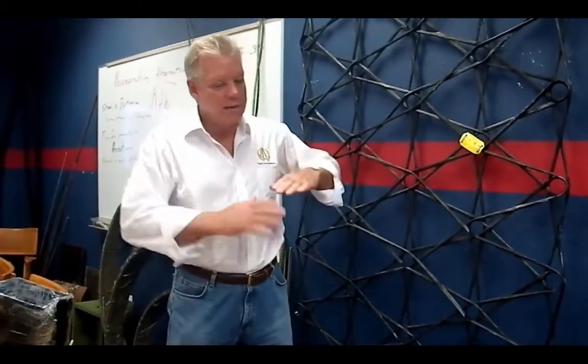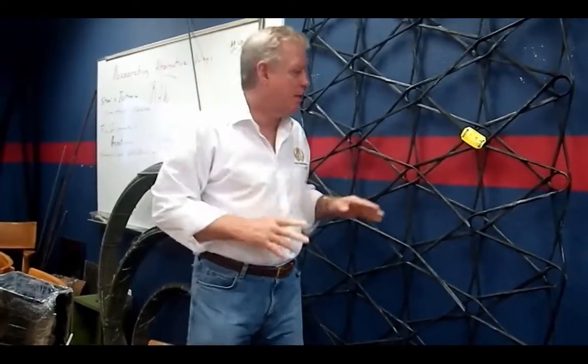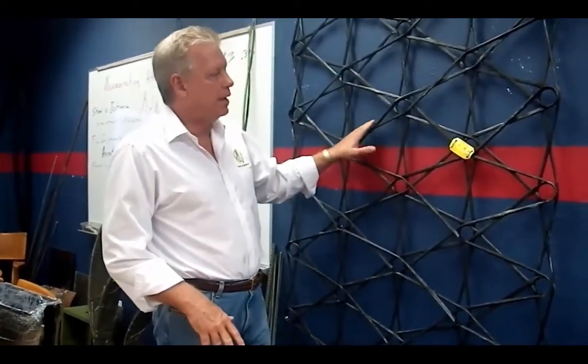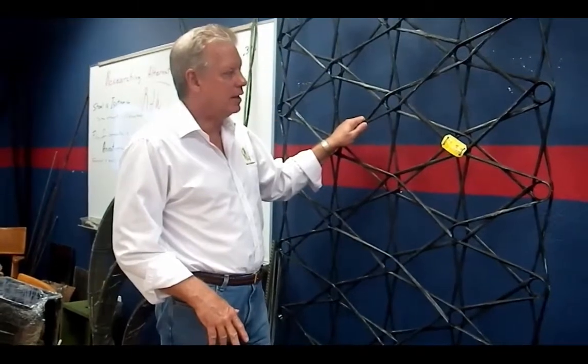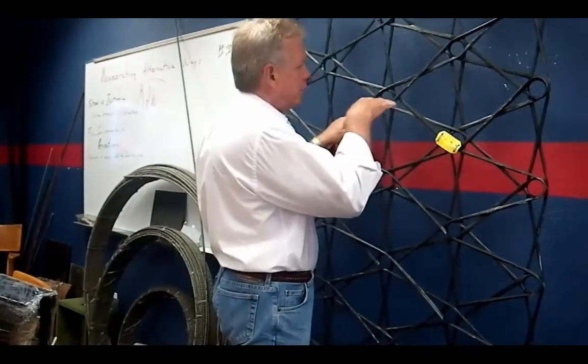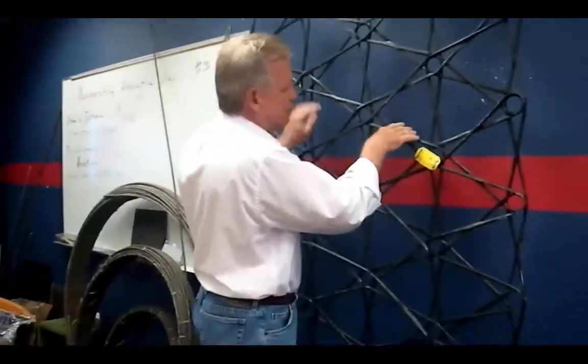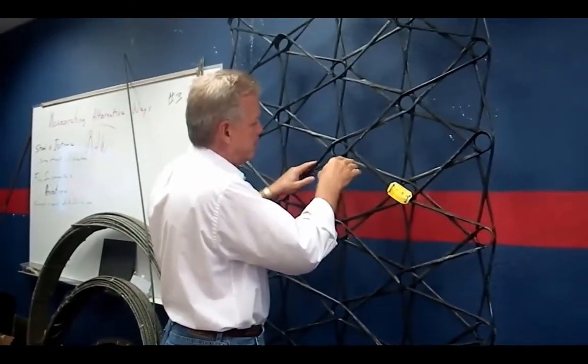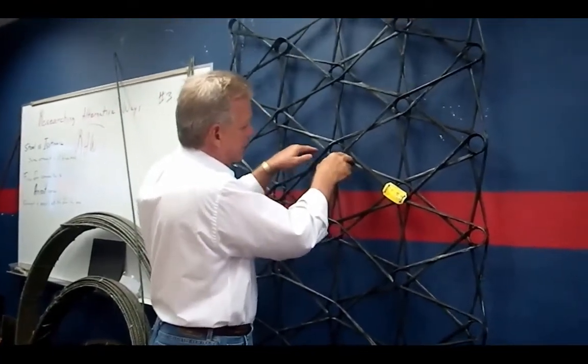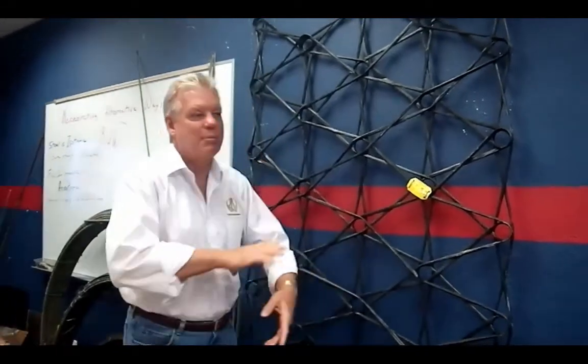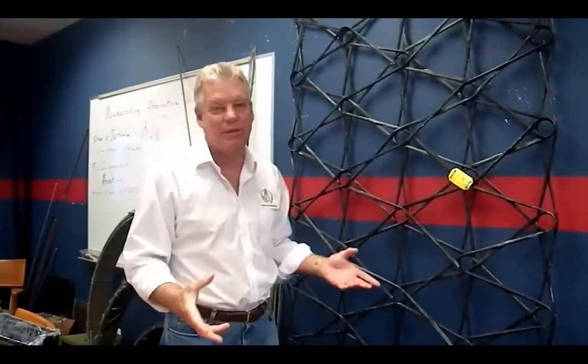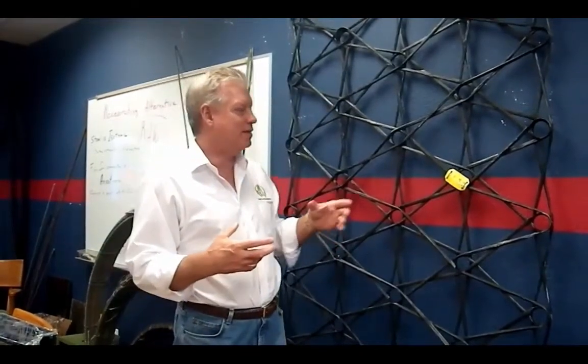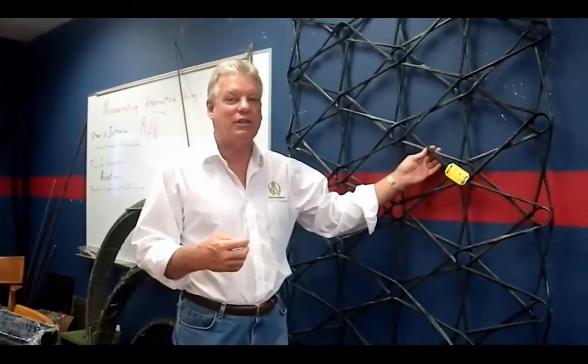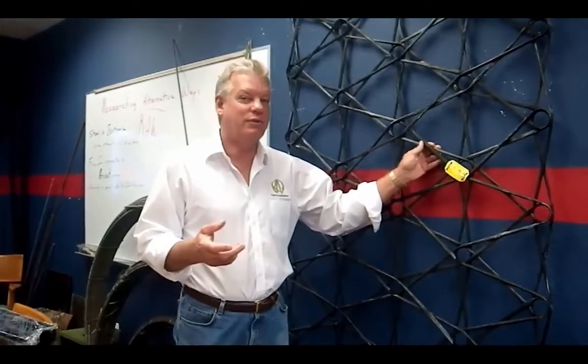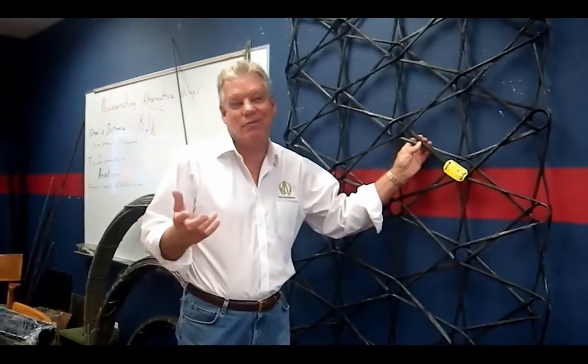Well, with the advent of rock DNA, we can go in at the bottom of the slab, at the bottom of the bending moment, and right above the road bed, apply a layer of rock DNA, and the concrete, when it's poured, goes through all these holes. Because it goes through the holes and it gets to these intersections, it's mechanically locked. We don't have a slip issue. This is not relying on the adhesion, the bond strength to the pervious concrete, not really at all.